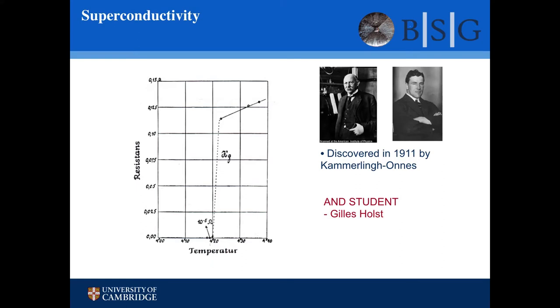And at 4.2 Kelvin, this resistance vanishes. And you can measure resistance by inducing a current to flow by applying a magnetic field and then monitoring the magnetic field. And one experiment, again in Holland, took a superconducting loop of material, created this magnetic field and monitored it for 7 years without any decay. So this really is a zero resistance state. It's extraordinary.